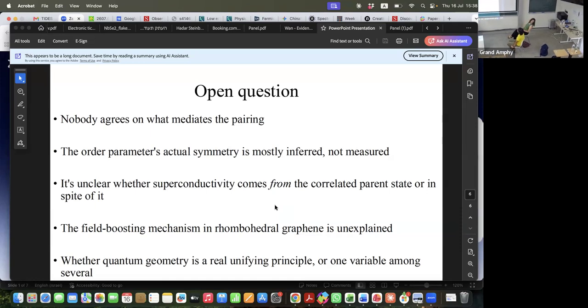Yes. There are a few theories going around. I don't know if they are correct or not, but one of them, developed by Gal Shavit, was saying that as you apply a magnetic field, you shift the spin Van Hove singularity. If you have a large density of states for both spin up and spin down, then you have the Stoner instability. When you apply a magnetic field, you separate them. So now one of the spins can have higher density of states and give the option for superconductivity.